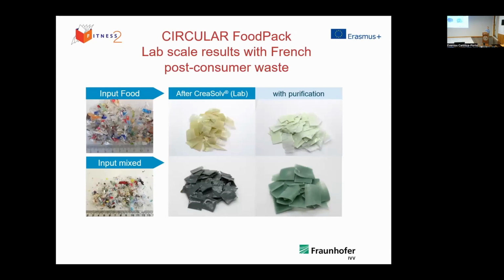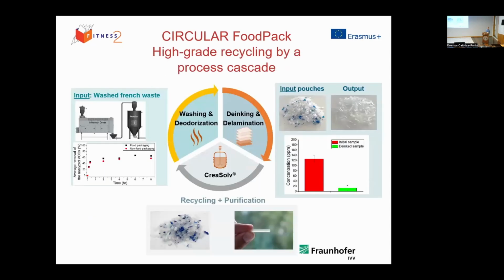And in this slide you can see that we have done tests with input coming only from food packaging and input from mixed packaging, and you can already see a difference here. If you have sorted really only food packaging materials, you get a very, very pure product in the end. But if you have a mixed waste stream, which is currently the case, the product doesn't look that good, and you have many contaminants inside. And we want to fix that with a process cascade, including the washing and deodorization, the de-inking and delamination, and the Creasolv process, which also includes the purification.